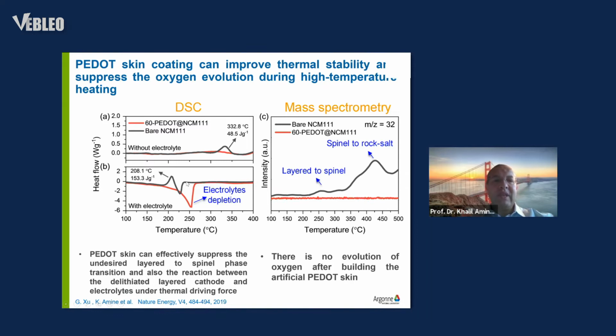Now, if we just take the electrode without electrolyte, charge it to 4.6 and heat it up, you can see the material without protection decomposes and generates some heat, while the coated material did not show any decomposition.